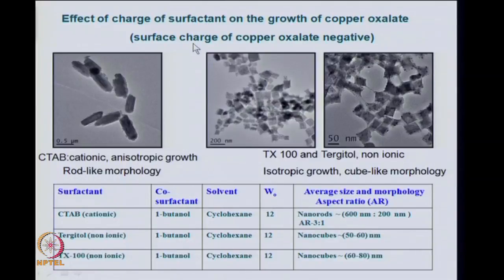And this is the surface charge, the charge of the surfactant. So, you have positive charge in C-tab and you have neutral charge in TX100 and tergitol, which are non-ionic, and here you see isotropic growth, whereas in the cationic surfactant you see more anisotropic growth. So, the aspect ratio is nearly 1, they are cubic in nature, whereas the aspect ratio is here 3 to 1.